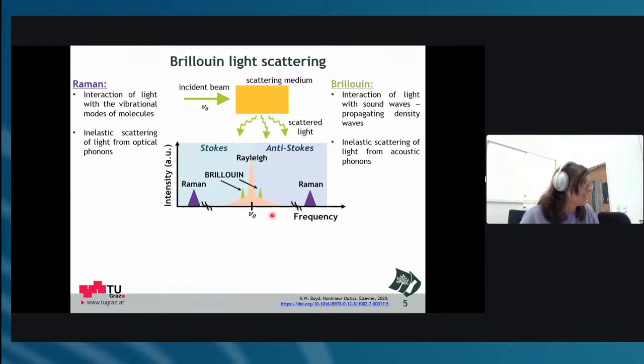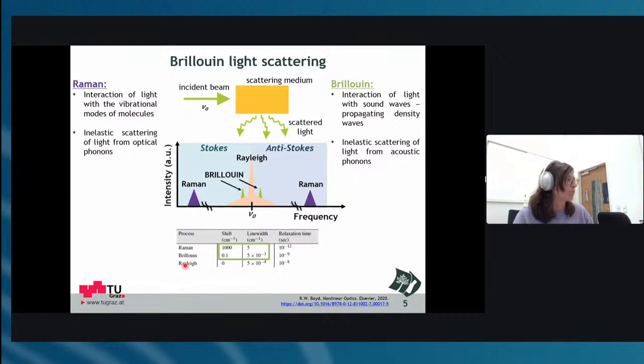And here is the thing, you cannot measure Brillouin with a Raman device, because due to this lower energy, these peaks are very tiny. They are usually very small and very close to the Rayleigh line, and you cannot get that resolution with a Raman instrument. Here in the table, you see it a bit more clearly. Raman is really far off of the zero line, and Brillouin is very close. And the line width, so the width of the peaks, is also much larger in the Raman signal.